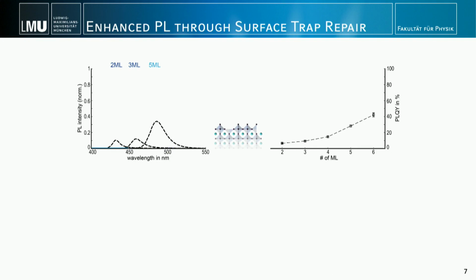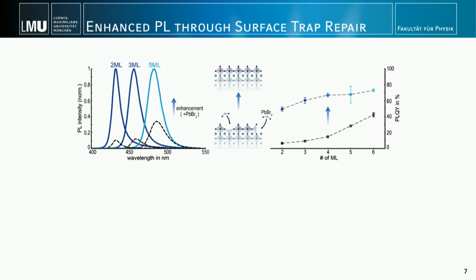Now, we were also lucky, that's also needed sometimes. We found that by adding lead bromide, we can actually repair these. So we call this the surface trap repair process. After the repair process, we measured the PL again. You see this quick rise, arrows pointing up, and now we had efficiencies between 50 and almost 80%. Now this was a reasonable value. At that time we reported and published it, these were the highest efficiencies for emission of blue perovskite crystals.